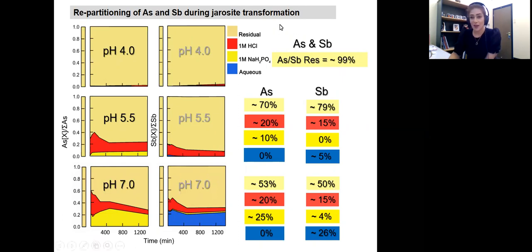And what I noticed was that these two trace metalloids not only behave differently from each other under different pH conditions, but they also behave very differently from each other under similar pH conditions, which actually contradicts the former assumptions that these two metalloids should behave similarly. So at pH 4, because we didn't have the mineralogical transformation, we didn't expect that much change in the repartitioning of arsenic and antimony, and that was the case. So with pH 4, everything was all right.